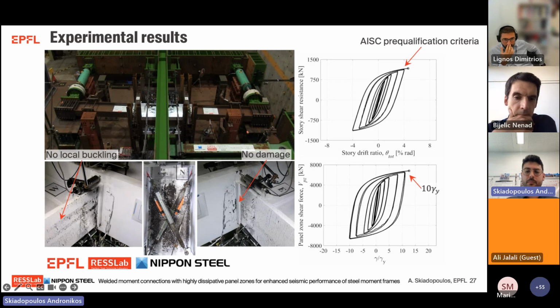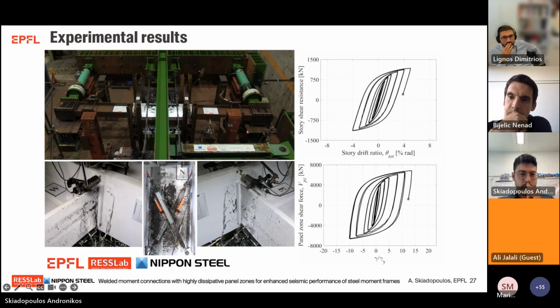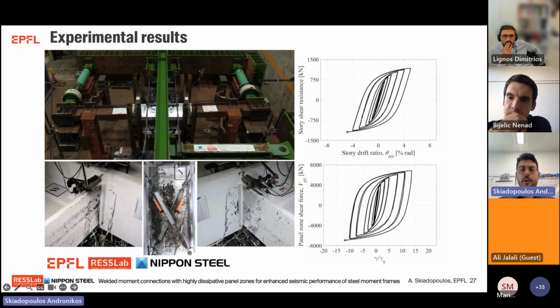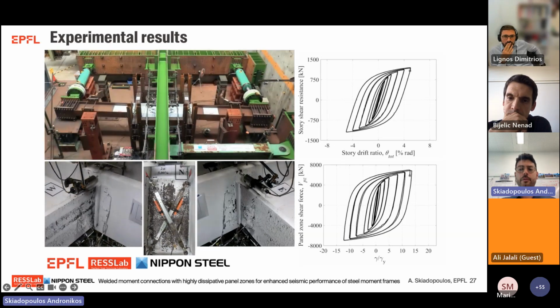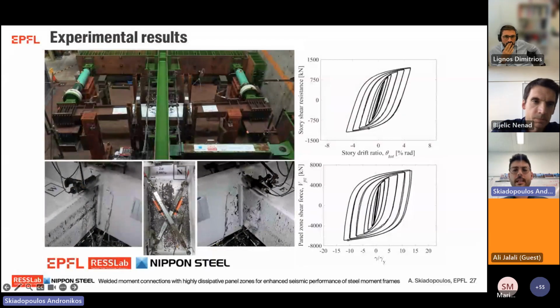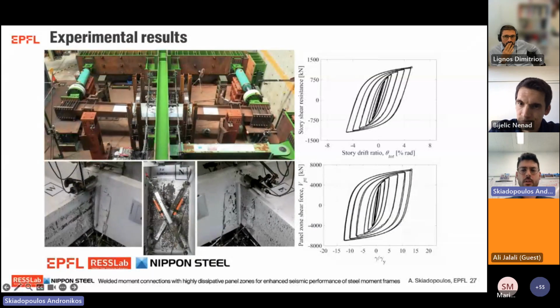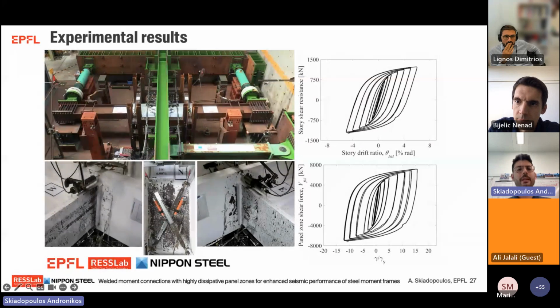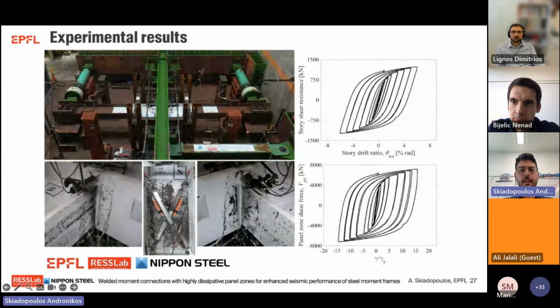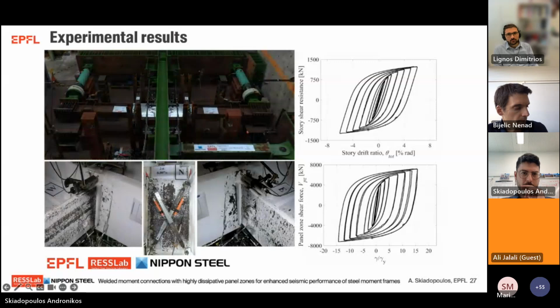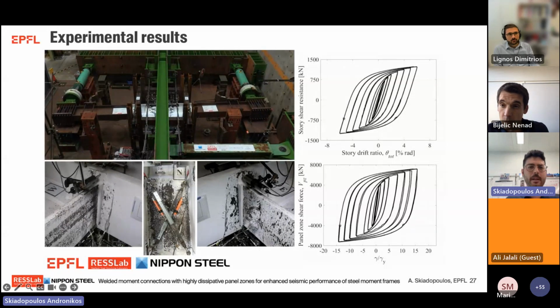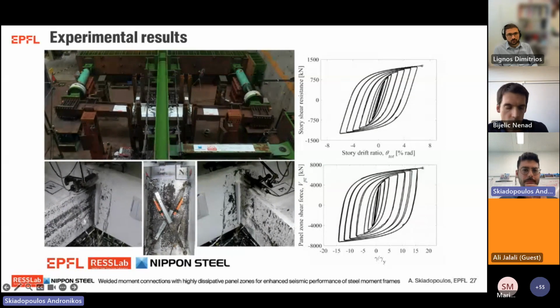And finally, at this drift level, the pre-qualification criteria of the American code as well as Eurocode Annex E are satisfied. Upon further loading, the onset of beam local buckling initiated at 5 to 6% story drift ratio. And even at this lateral drift demand, there was no identifiable damage in the proposed beveled backing bars.